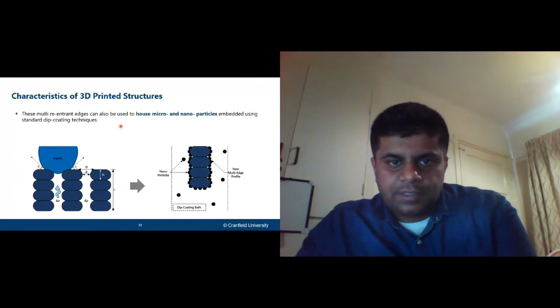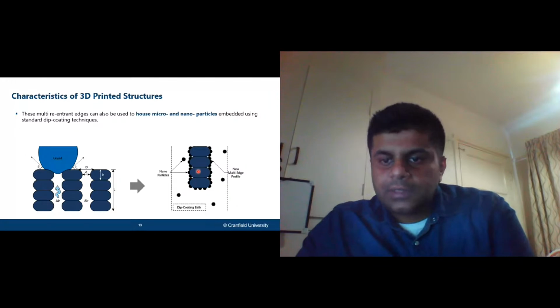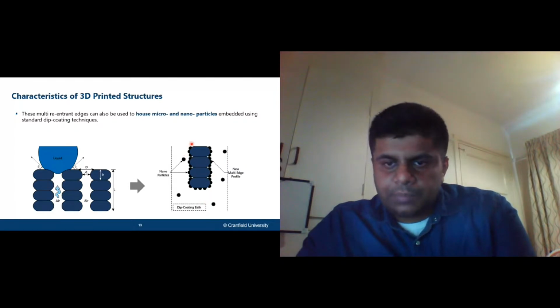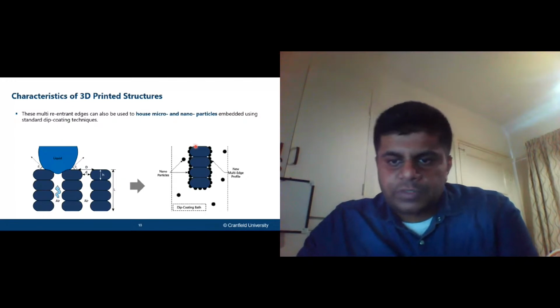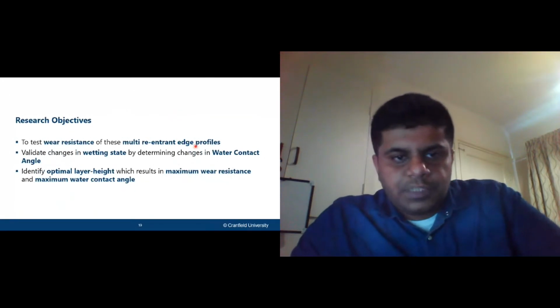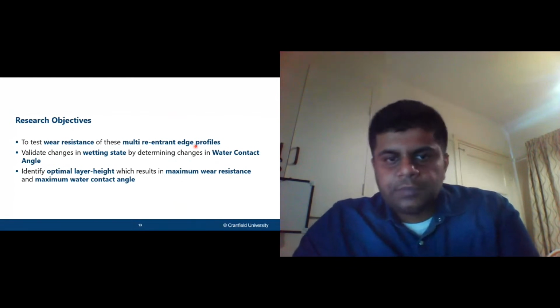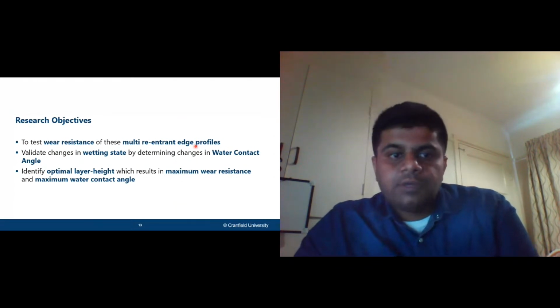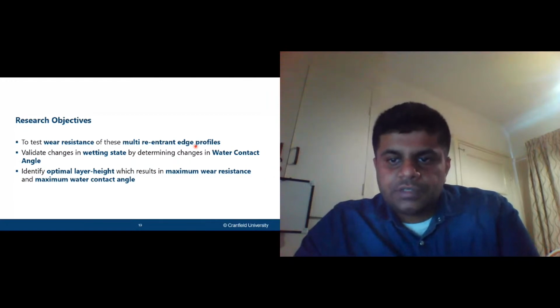And these multiple reentrant edges can also host micro and nanoparticles, as shown over here. So if you use a dip coating or spray coating application, you can also stack more particles like nanoparticles over here to create further reentrant edges on these sides, like shown here. In this way, you're going to end up with multiple profiles that can support any kind of liquid on top of the surface. So for this particular experimental investigation, we wanted to test the wear resistance of the multi-reentrant edge profiles. We wanted to validate changes in wetting state by determining changes in water contact angle. And we wanted to identify the optimal layer height, which results in maximum wear resistance and maximum water contact angle.